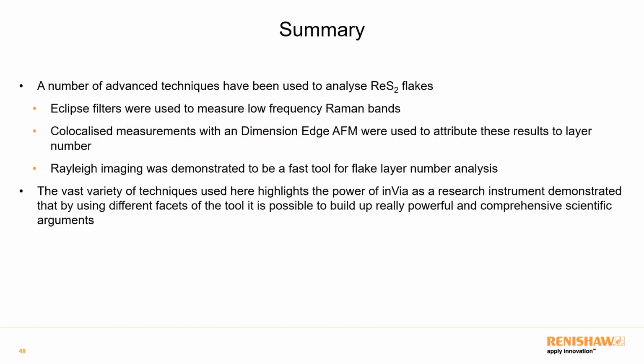Now I'd just like to summarize this case study. We've used a number of techniques to analyze the rhenium disulfide flakes. We used Eclipse filters to measure low wave number Raman bands. We also did Raman mapping using these filters. We did co-localized measurements with a Dimension Edge AFM, and we used this to get the sample topography and correlate flake thickness with the Raman data.